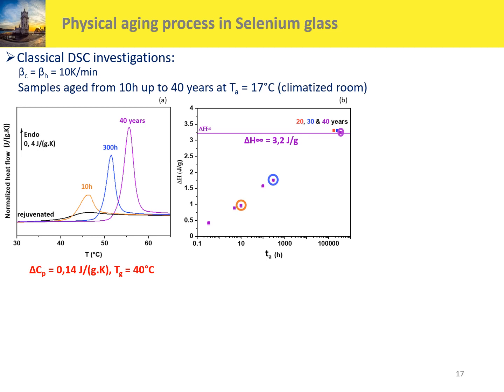So now, what about the physical aging process in selenium glass? First, we started by classical DSC investigations with samples aged from 10 hours up to 40 years at, in fact, 17 degrees C. These are the experimental curves that we have obtained and the enthalpy loss that we have calculated.